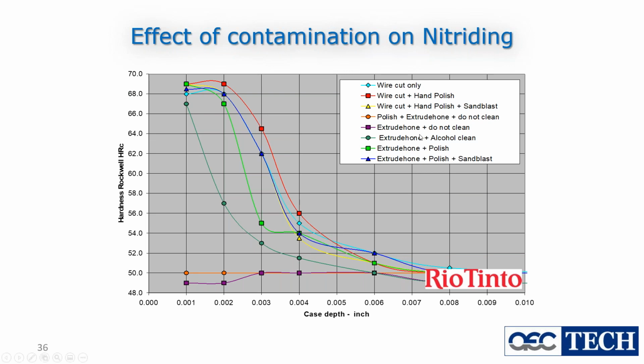If you clean the extrude hone with alcohol, you think you've done a pretty good job. It looks pretty clean, but look, it's still an outlier. It's good, the surface is good. If you hit the surface with a surface indenter or scratch it with a file, you'll get the same result. But under the surface, subsurface, it's really not nitrided to anything like the same depth.